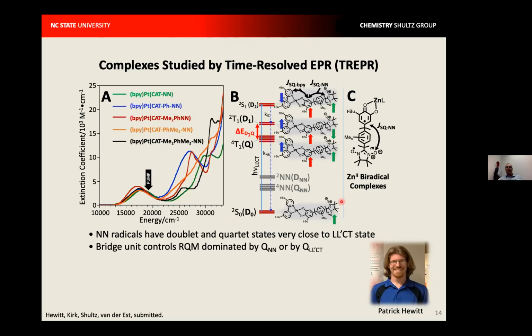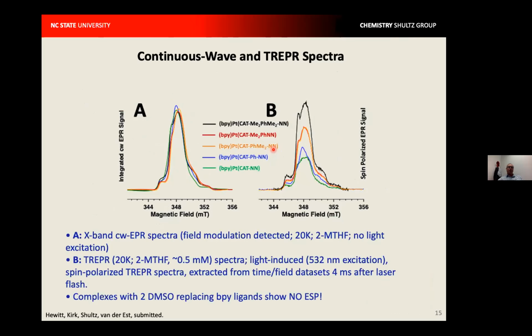And so I went too fast there. What's happening when we change these bridges is we're changing the energy gap between the quartet and doublet synthetically, but then we're also getting the effect of reduced energy gap by certain conformations that we see by freezing the solution and not allowing the molecules to relax to their equilibrium geometries. So all of the EPR experiments here are done in frozen solvent solutions.